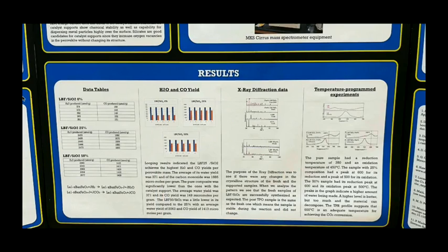Also, the activity of oxygen vacancy sites during carbon monoxide formation is closely related to the net number of oxygen vacancies at any time. So this means that the higher the availability of oxygen vacancy sites, the higher the carbon dioxide absorption over a perovskite. But as carbon dioxide converts to carbon monoxide, the sites do not get replenished, which causes a gradual stagnation of surface exchange kinetics and results in less carbon monoxide production than water in the first cycle.